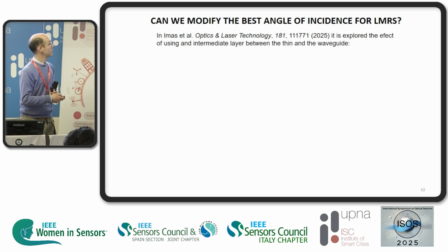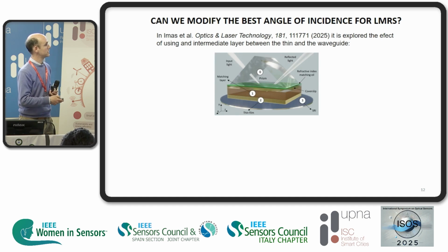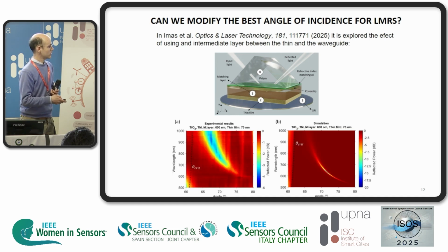In a work published recently by José Javier Imas in Optics and Laser Technology, he explored the use of an intermediate layer between the thin film and the waveguide. So the idea is this setup. In a Kretschmann configuration, we have the optical prism, we impinge the light, and we have the thin film, but between the waveguide and the thin film we have a matching layer, an intermediate layer. Here he explored the effect of this matching layer when we deposit titanium, both experimentally and with simulation, and we observe that the resonance is more visible around 70 degrees.